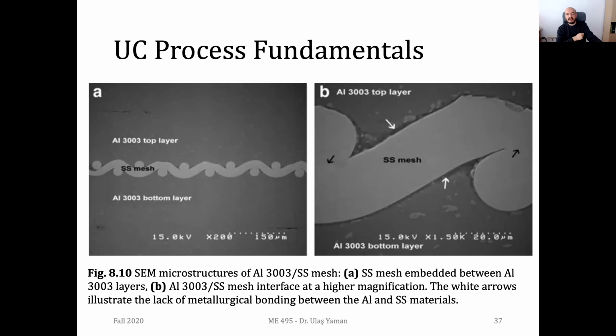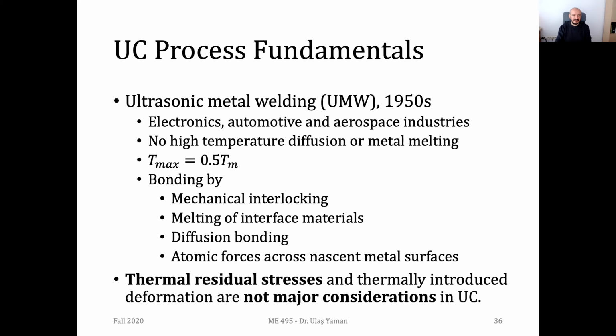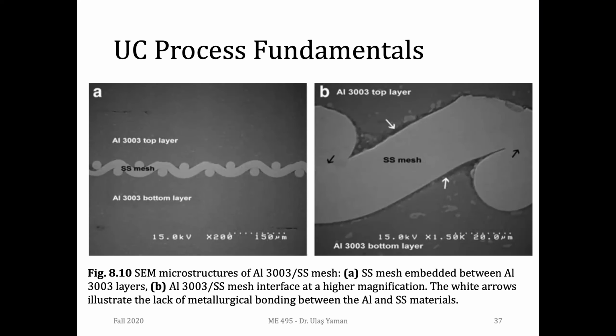Yes, otherwise you cannot apply the vibration to the interface clearly. If the thickness is too much, then you cannot join them. You cannot obtain this mechanical interlocking or diffusion. You cannot start plastic deformation at the interface. So here you see we have sheets of aluminum, bottom layer, top layer, and in between we are embedding a stainless steel kind of mesh.